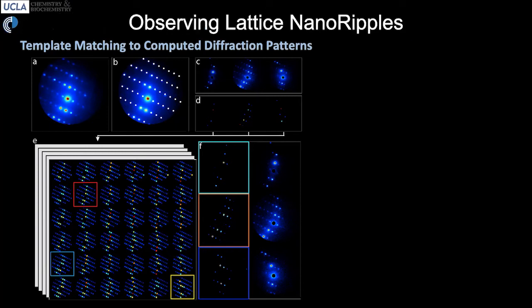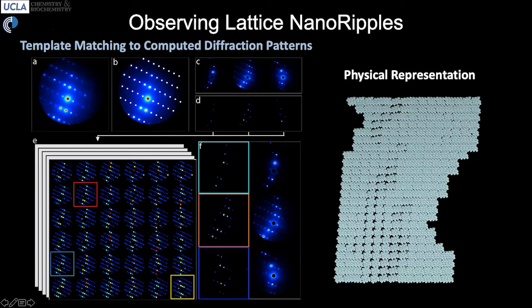And so when we put all of this information together, what we could see is that while quite a high number of the patterns across the scan represented the lattice being at a particular orientation in space, what we could, in a hypothetical world, imagine there existing is ripples in that lattice that displaced the orientation of that lattice with respect to the consensus orientation. And this is what this picture tries to show. It just shows the molecule that presumably we would be sitting in this lattice at a particular orientation. And you can see that molecule being reoriented in space as a result of this rippling phenomenon. And so you can see the ripples here in space across the crystal. Of course, we are not visualizing ripples in individual molecules. This is just a representation of what's happening across that crystal.